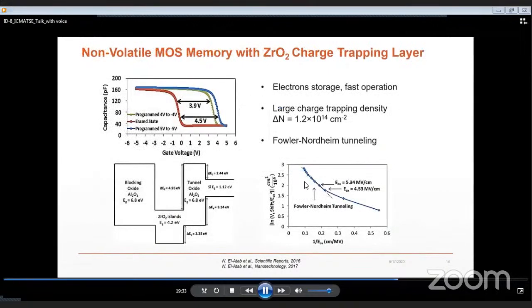Memory devices using nano islands as the charge trapping layer have been fabricated and characterized. The memory devices are electrically characterized using high frequency CV measurements. A large memory window of 4.5 volts is achieved at a small program voltage of 5 volts. In fact, the high dielectric constant of the zirconia nano islands with cubic phase leads to a large electric field across the tunnel oxide, which results in a large memory window at low operating voltages.